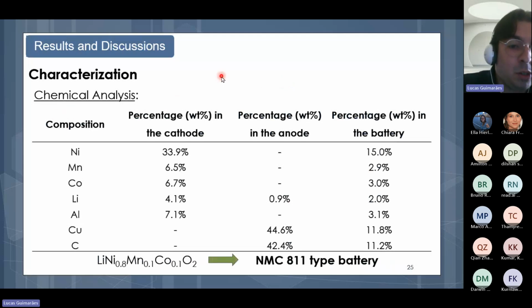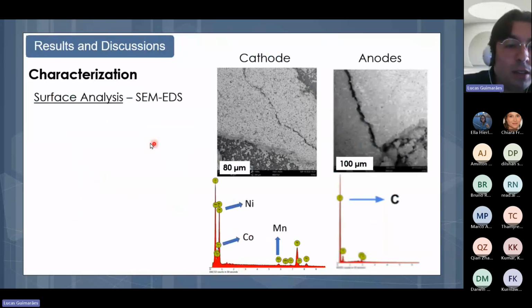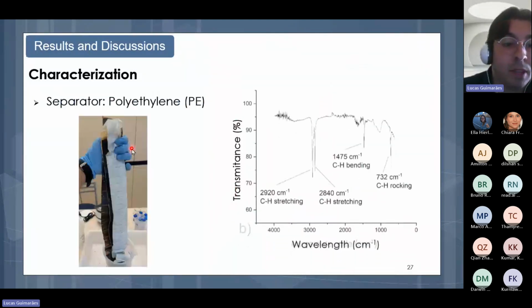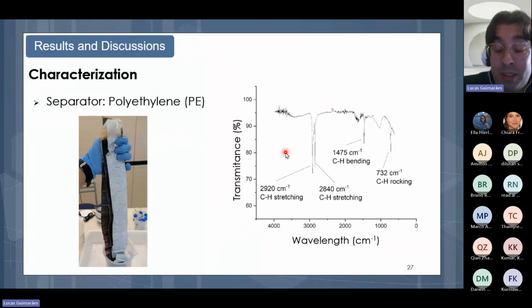And the chemical analysis corroborated the previous results, in which we could find in the active material of the cathode nickel, manganese, and cobalt, and therefore we could determine that the type of that battery was NMC 811. Once again, the analysis made on scanning electron microscope found nickel, cobalt, and manganese again in the cathode, and graphite in the anode. For the separator, the FTIR analysis found polyethylene as the material of the separator.